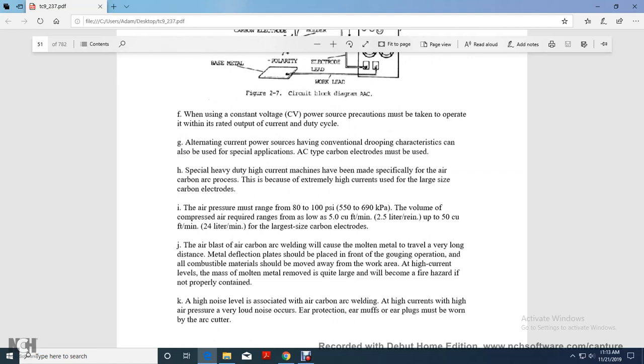Alternating current power sources have the conventional drooping characteristics and can also be used for special applications. AC type carbon electrodes may be used. Special heavy-duty direct current high-current machines have been made for the air carbon arc process because extremely high currents are used with large size carbon electrodes. Air pressure must range from 80 to 100 psi. Compressed air volume ranges from as low as 5 cubic feet a minute up to 50 cubic feet a minute with larger size carbon electrodes.